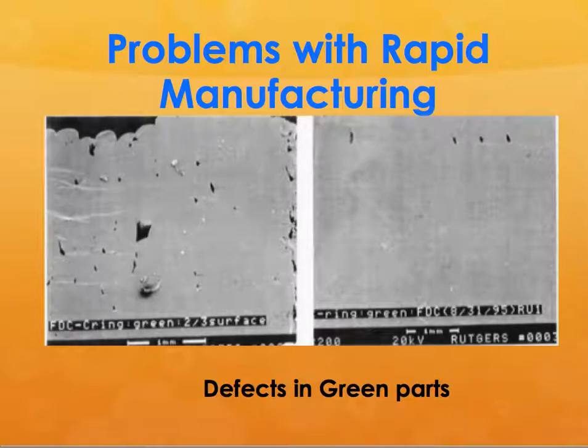So what did I tell you? What are the problems with rapid manufacturing, especially if it is a ceramic? You will have defects in the green parts. Because this is a stair step feature, you have these steps in the part, so it doesn't give you a nice clean finish. That's the first problem. And the second problem is that you can have subsurface flaws.